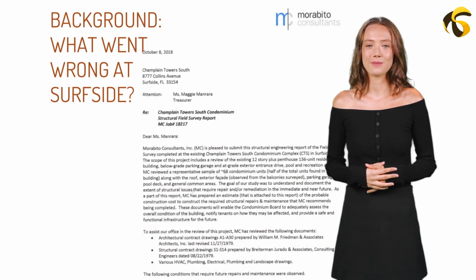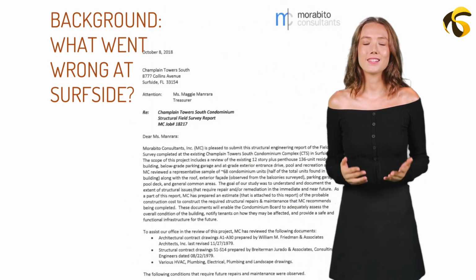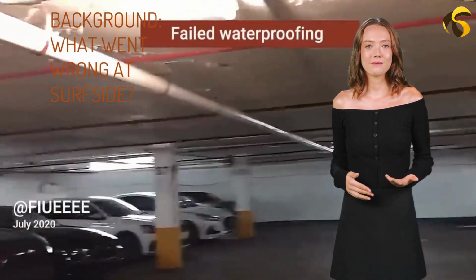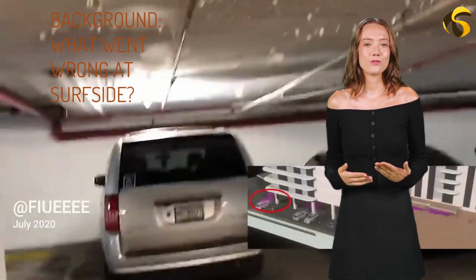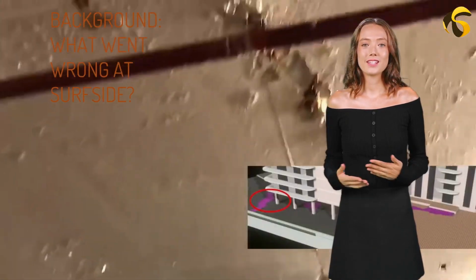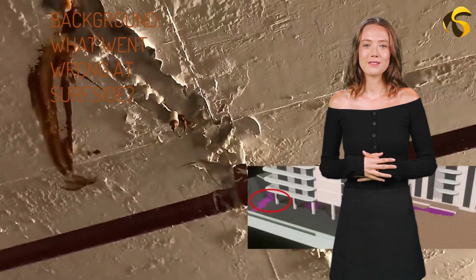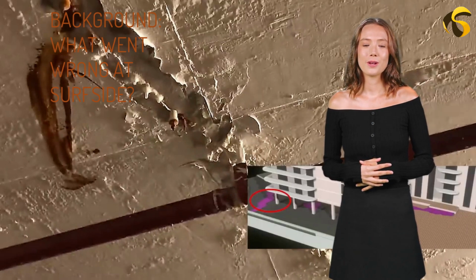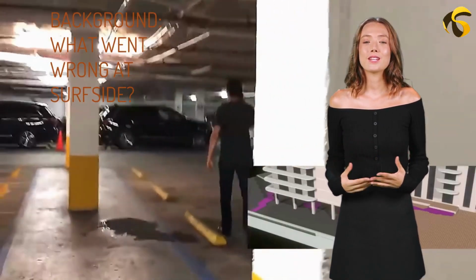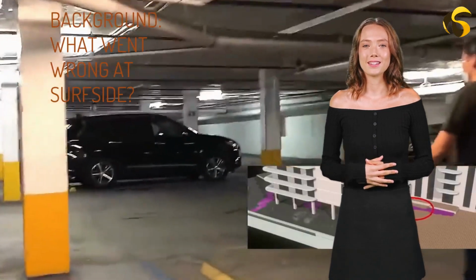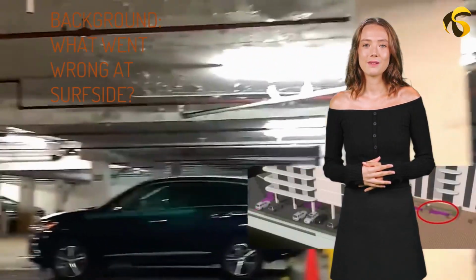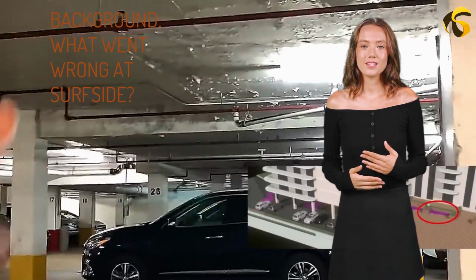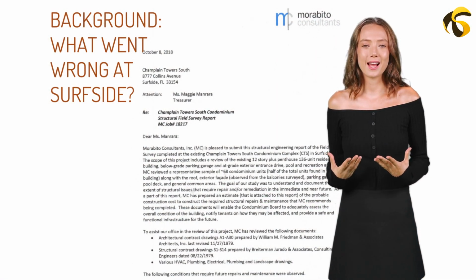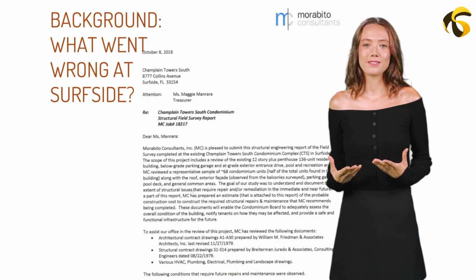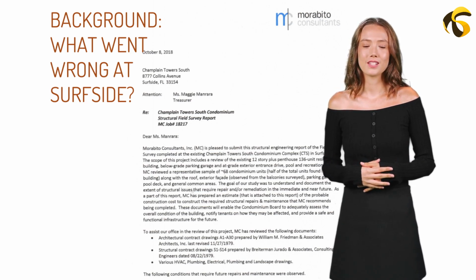Multiple investigations by engineers, Miami-Dade County, and NIST are ongoing, but a consensus is emerging that water-induced damage played a central role in the Surfside collapse. In particular, attention is focused on the pool deck and parking garage areas, where evidence of long-term water penetration and concrete deterioration was well documented years before the collapse. In October 2018, an inspection by engineer Frank P. Morabito revealed major structural damage in the concrete slab beneath the pool deck, as well as extensive cracking and spalling, concrete breaking apart, in the parking garage columns.